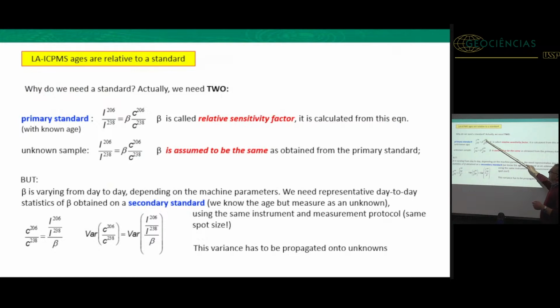so we need to calibrate this. So we need to calibrate this using a primary standard. We know exactly the age, and this age has to be an ID-TIMS age. And then we establish between this ratio and this ratio is an offset, and this offset is the beta, which is called the relative sensitivity factor. It's all fine. Every lab does this. But then we take an unknown sample, we do the same thing, but we do this by assuming that the beta is the same. With this unknown, who has a different age, different uranium concentration, different trace element composition, we assume that this has the same beta as this one.